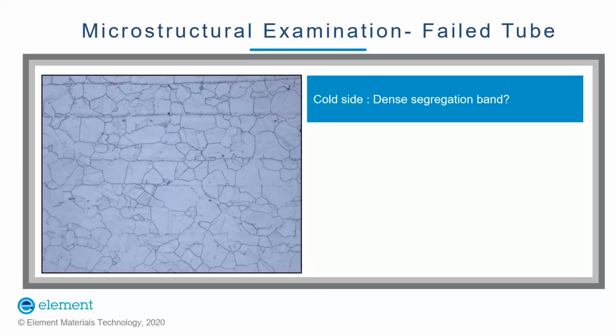Detailed microstructural analysis was done on this failed tube. Analysis was done both at the hot side, where a crack was observed, and also at the cold side, where there was no failure or crack observed. A detailed microstructural comparison was done for these two locations and is presented in this slide.